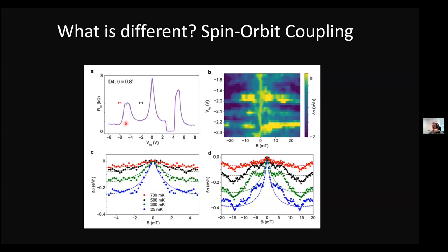So basically, you take some small density range or backgate voltage range, and you sweep around small magnetic field. And if you have spin-orbit coupling, you are expected to observe this peak close to zero magnetic field, and this is due to interference effects. So we found this in the D4, 0.8 degrees device. We found the spin-orbit coupling present both in the flat bands and also in the dispersive bands. This is definitely present, and when you think about the system, you cannot really completely ignore it.